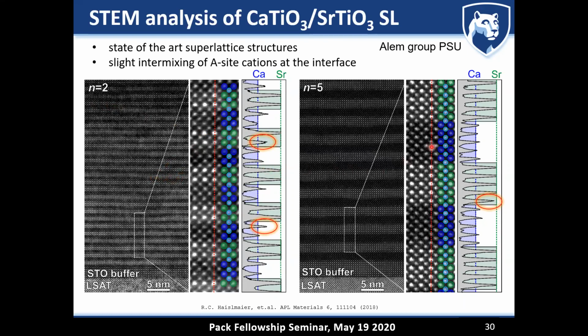In fact, if you measure the abruptness of these interfaces just by looking at the Z contrast along these lines, you can see that everywhere where we have a calcium titanate, this is the little darker one, you can see that the intensity along the lines of the A site is going to be roughly of the same intensity, while the intensity of the STEM contrast for the strontium line is also fairly constant. Sometimes you see a little bit of a deviation. This deviation here for the n equals 5 was not as strong as for the n equals 2 superlattice, and we attribute this to not the precise timing. So there was a little bit of intermixing at those interfaces.